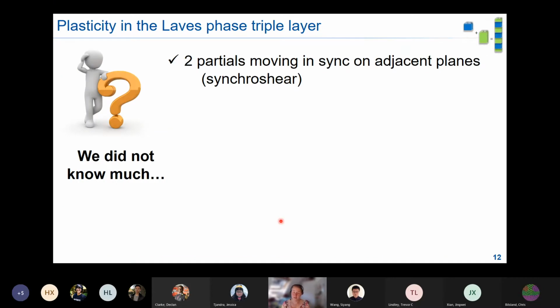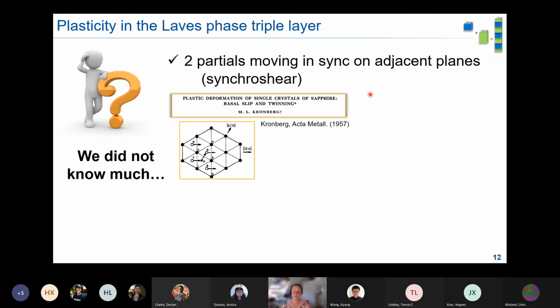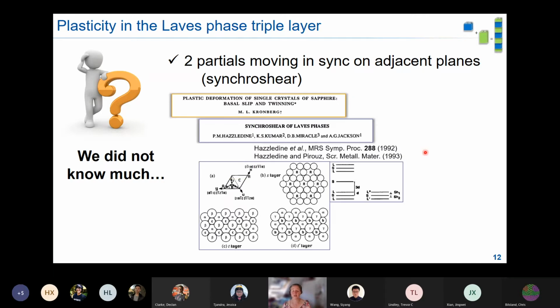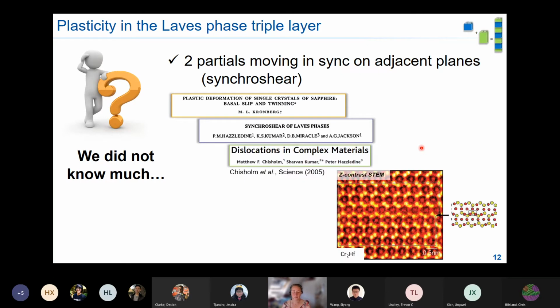That process, we didn't come up with this process. That process had been known or had been suggested actually quite a while ago. It's called synchroshear, and it was first suggested for sapphire. And then in the 90s, it was suggested that this actually might happen in these Laves phases on the basal plane as well. The problem was that until, well, now maybe not that recently, 16 years ago, nobody had actually seen it. And in 2005, there was a Science paper that essentially just looked at a dislocation and showed the stacking fault that's consistent with this mechanism.